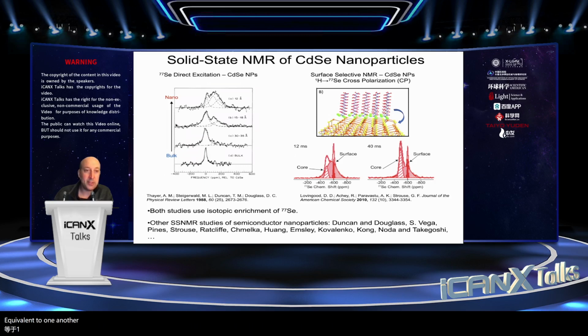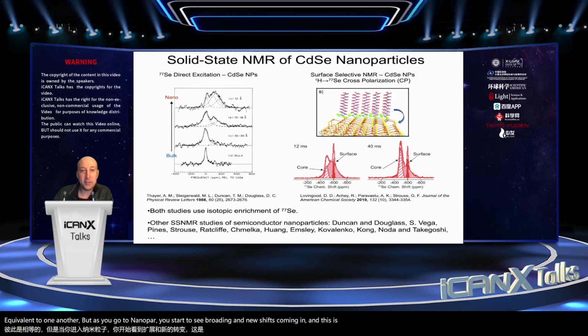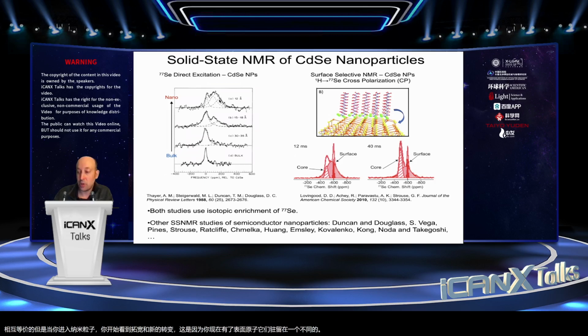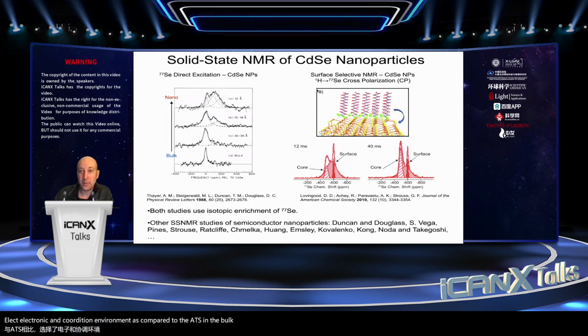But as you go to nanoparticles, you start to see broadening and new shifts coming in. And this is because you're now having surface atoms which reside in a distinct electronic and coordination environment as compared to the atoms in the bulk. This is some nice work from Jeff Strouse's lab at Florida State University. What they did here are some proton to selenium cross-polarization solid-state NMR experiments. This is a nice experiment because it provides surface selectivity.